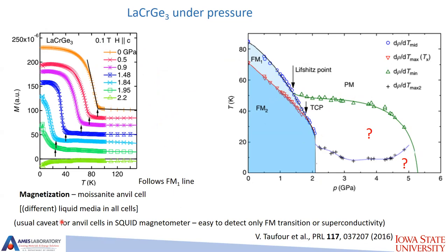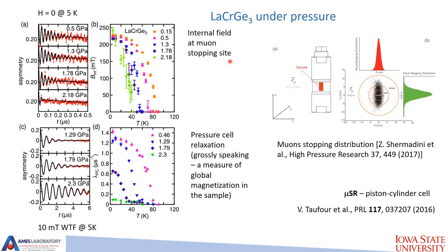Now, these measurements were done in a moissanite anvil cell, in a SQUID magnetometer. So there is a usual caveat for such measurements. It's easy to detect only ferromagnetism or superconductivity. So the fact that we don't see this line in these measurements doesn't mean that it doesn't exist. It's just not ferromagnetism and not superconductivity. But that's probably known to the majority of the people in this talk. Let's go further.